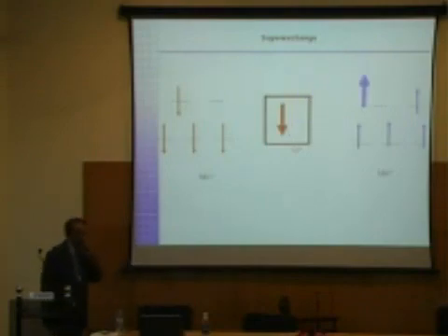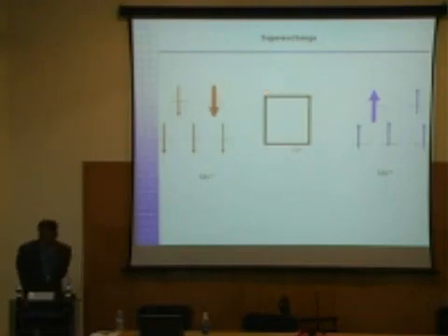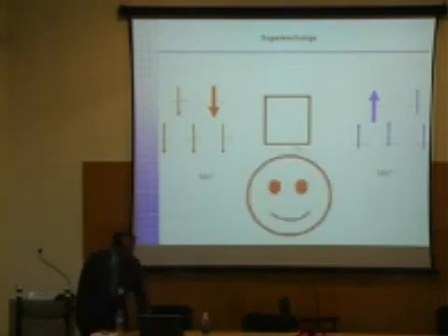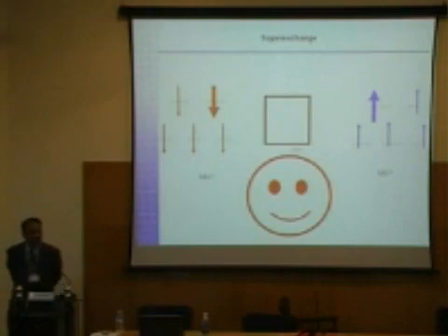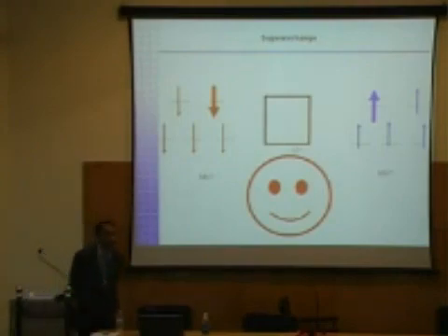Again, I'm going to transfer one of the electrons from oxygen, and you see I'm not violating any of the Hund's rules here. So as a result, whenever you have two manganese 3+ ions next to each other, the ordering generally tends to be antiferromagnetic, not ferromagnetic. In fact, I have examined hundreds of manganese 3+ compounds. I'm yet to see any manganese 3+, oxygen 2-, manganese 3+ showing any ferromagnetism. So typically, we all see only antiferromagnetism.